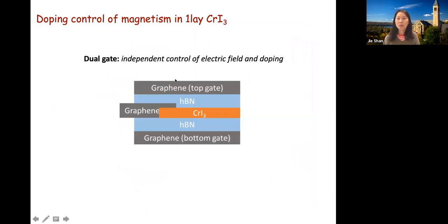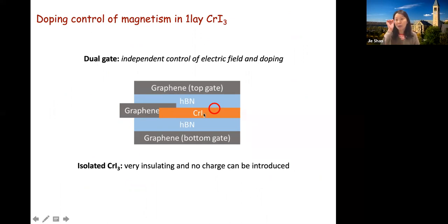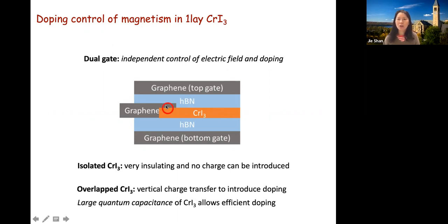So now we put the structure in a two-gate geometry. Because this chromium iodide itself is very insulating, if you apply gate voltage here and there, you almost don't dope it, because charge cannot flow into it. But if you look at the area overlapping with graphene, you can have charge flow into graphene and graphene jump into chromium iodide. So this overlapped area can be heavily doped because chromium iodide has very flat band, so it can hold a lot of charge. Let's take a look at the doping effect.